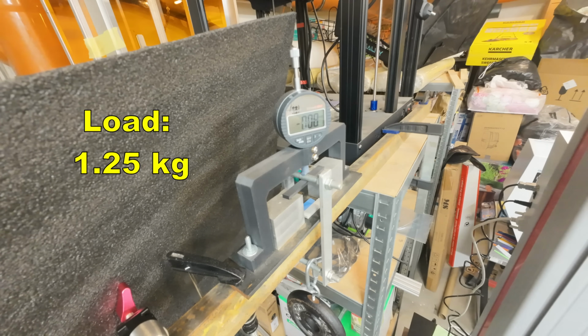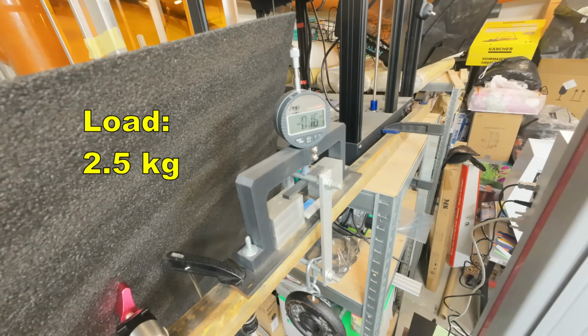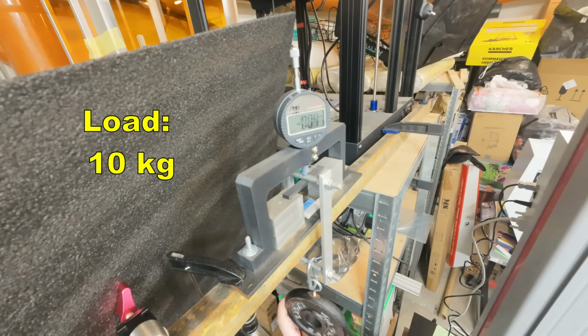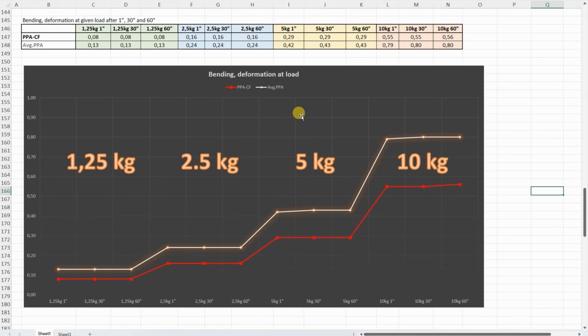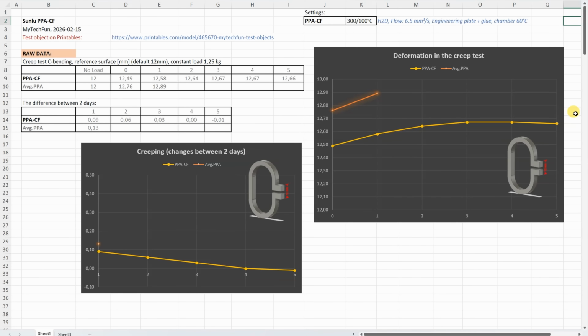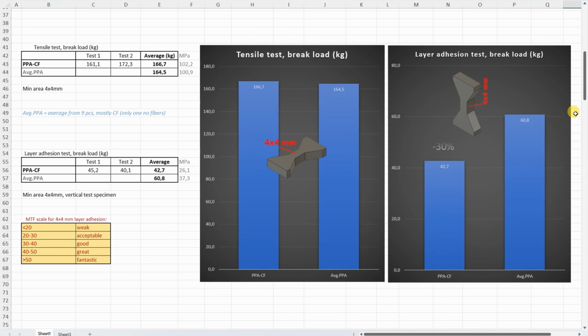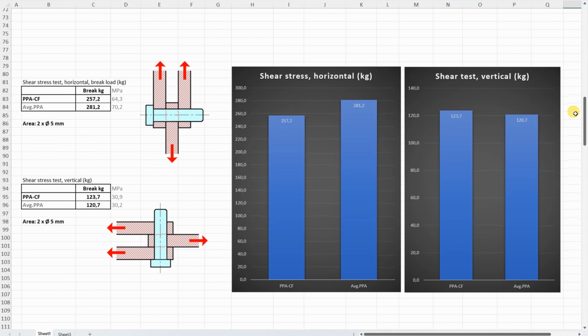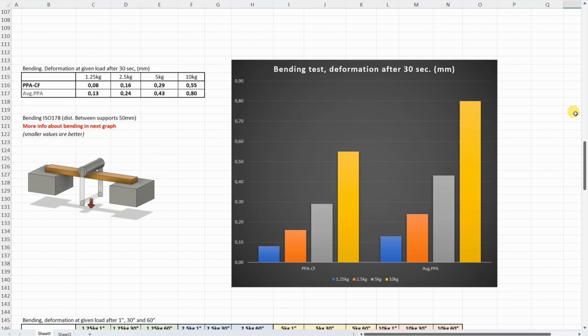3-point bending test. Distance between supports is 50 millimeters, and I'm placing these loads and measuring the deformation after 1, 30 and 60 seconds. This is under 5 kilograms, 10, very minimal deformation, and basically no changes during this 1 minute. Every PPA filament is very good in this test, and look at this PPA-CF, significantly smaller deformation, extremely similar to the Bambu PPA-CF, which, as you can already check in my summary table, is the stiffest material I ever tested, and this one is extremely similar.